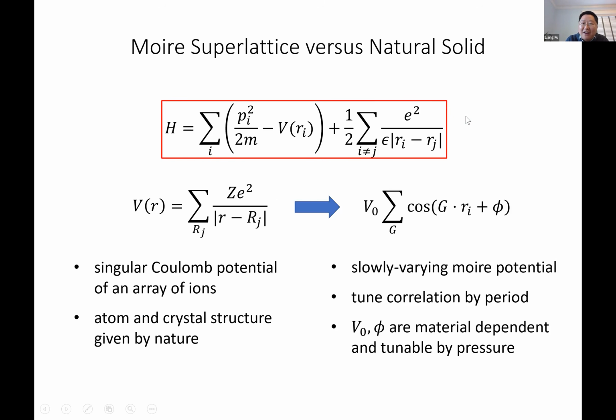On the other hand, if you look at this TMD Moiré superlattice, again we have kinetic energy with Coulomb interaction, but now instead of the Coulomb potential, we have a smooth, slowly varying Moiré potential, which is nothing but a sinusoidal potential. And in this case, one can tune the strength of correlation by the twist angle. As you move away from 0 degrees, the Moiré period decreases, so the effect of the potential becomes small compared to the kinetic energy. So a large period means strong correlation, because the kinetic energy of the Moiré band decreases. Moreover, this potential strength V0 is material dependent, and it can also be tuned by applying pressure. And this phi is actually the key parameter that I'm going to focus on. When you take the sum of 3 cosines, the sum of 3 Fourier components, there is an overall phase that determines the shape of this potential.